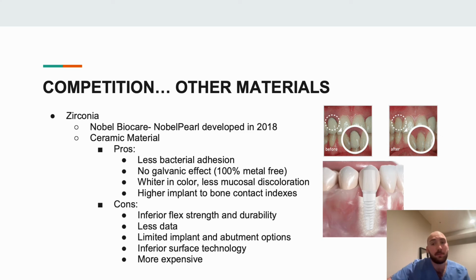One of the newer players on the block to compete with titanium-based implants are zirconia implants. Nobel Biocare developed an entirely ceramic dental implant named Nobel Pearl in 2018. This implant is made of zirconium dioxide, more commonly known as zirconia, which is metal-free. One of the benefits of choosing a product like Nobel Pearl is the fact that zirconia statistically demonstrates less bacterial adhesion than implants made primarily of titanium, meaning they have less plaque buildup.